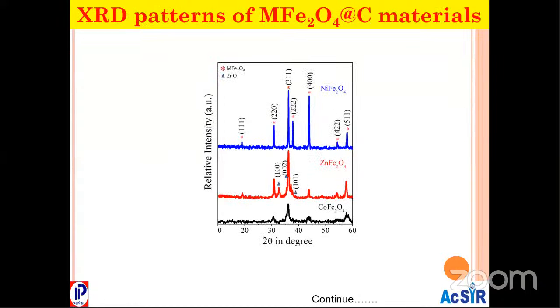These are the XRD patterns. As you are learning XRD, if in future you are going to do research, from XRD we will get information on the crystalline pattern of the nanoparticles. Here you can see that the XRD pattern shows the spinel structure was observed for all the cases. But in the case of ZnFe2O4, some impurity of ZnO was also visible.